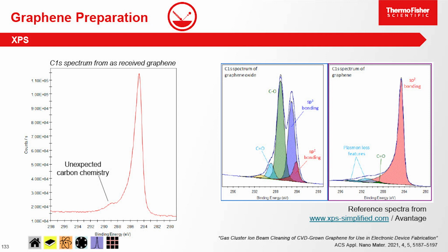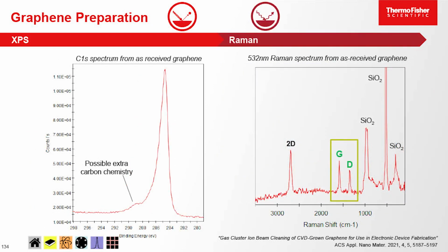So our graphene spectrum should look like this, but we're seeing a peak here which is unexpected chemistry. And the way this sample is prepared is it's grown on a copper substrate, then it's transferred onto polymethyl methacrylate, so PMMA, and then it's transferred from that PMMA onto the silicon wafer to prepare the device. And it's probably some of the polymer that's left on the surface of the material. So if we have a look with the Raman spectrometer, we can see the characteristic peaks of both the silicon substrate, so these three peaks here, but also the ones for the graphene.